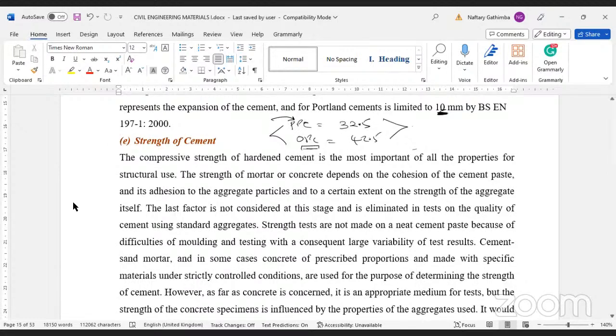Now, to get the strength of cement, we create a cube using cement. It could be 75 millimeters by 75 millimeters by 75 millimeters. These molds are standard, steel molds. It's a mold made of steel which you can demold, and you put your cement paste inside here. However, sometimes it's very difficult to make neat cement paste. When you mix cement in water, it sticks even to the trowel you're using, even to your hand. So what happens is that we use what is called a standard sand to make standard mortar.